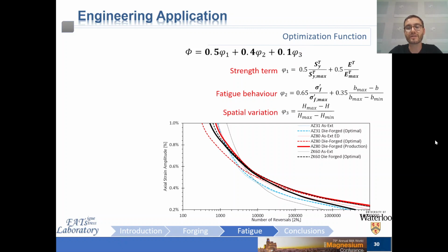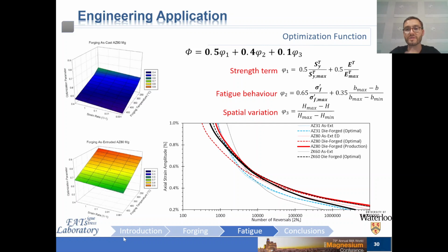Now calculating the magnitude of this objective function for all the investigated processing conditions, the following surface plots were generated to represent the optimization surfaces of each case. So this is cast forged at the top here and extruded forged at the bottom for AZ80 magnesium, which is the most forgeable version of the three alloys that we've investigated. Once again, a value of 1 here on the surface is technically optimal because each of the three terms in this equation are non-dimensionalized.